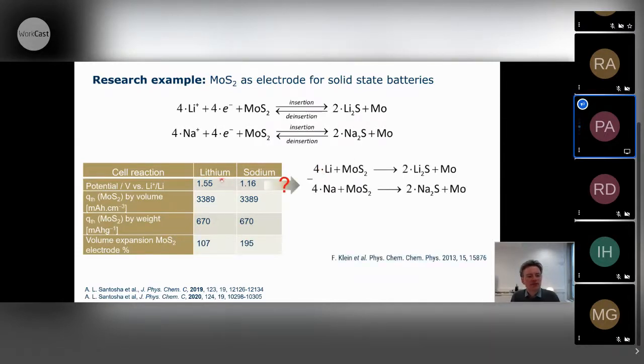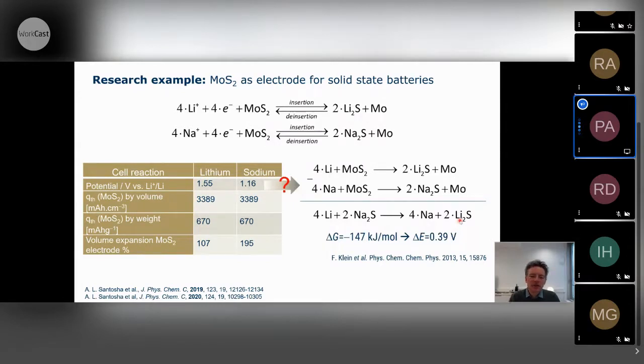You can see the difference between lithium and sodium is 0.39 volts, and the difference originates simply from this difference here. This is again the reaction for lithium and sodium. If you just build the difference, this would be the difference between both reactions, right? So lithium reacting with sodium sulfide to form sodium and lithium sulfide. From this, you can calculate delta G. And delta G relates to a difference in the cell voltage of these reactions, and 147 kilojoule per mole corresponds to 390 millivolts. This is exactly the difference that you have in theory between both reactions.